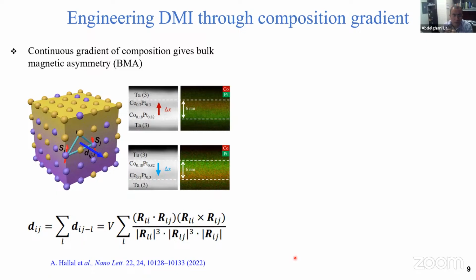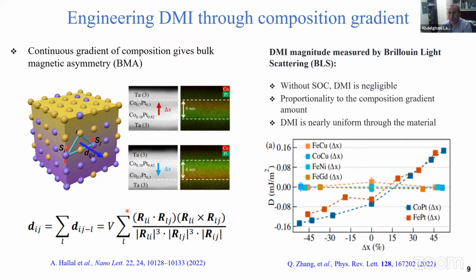Recently, there was another way to engineer DMI, and this is based on a continuous gradient of composition. In this case, for example, I show here cobalt platinum, where by changing the composition of cobalt from the upper surface to the lower surface at the substrate, this is a color map of the cobalt content. In principle, you induce what's called magnetic asymmetry. And this magnetic asymmetry, in addition to the spin orbit coupling created by the heavy metal in this case, or it can be rare earth as well, leads to this DMI interaction, so DMI forms. In this system, people used BLS.